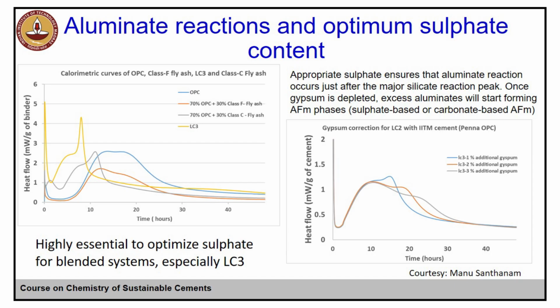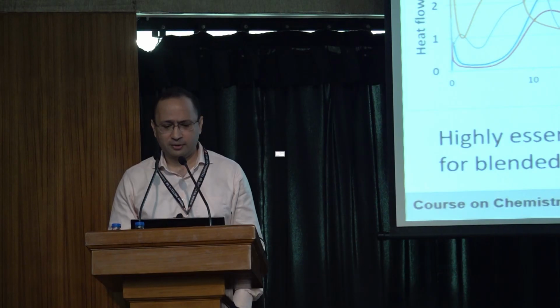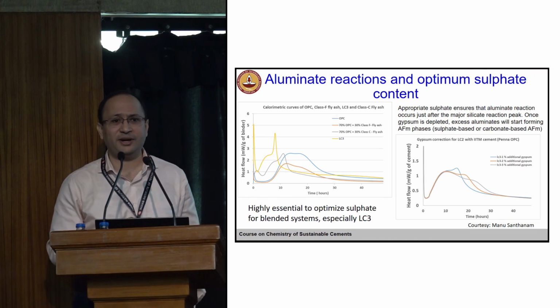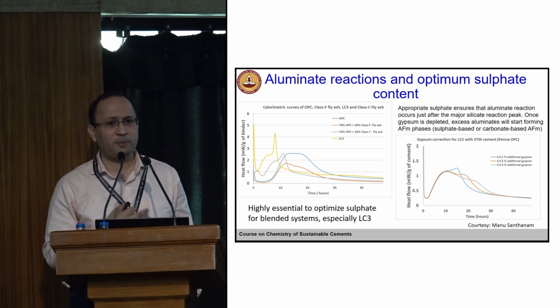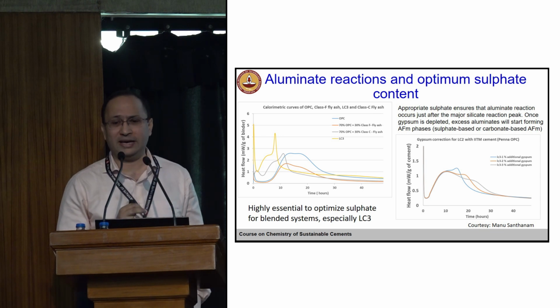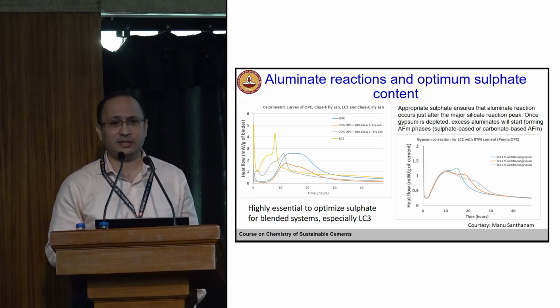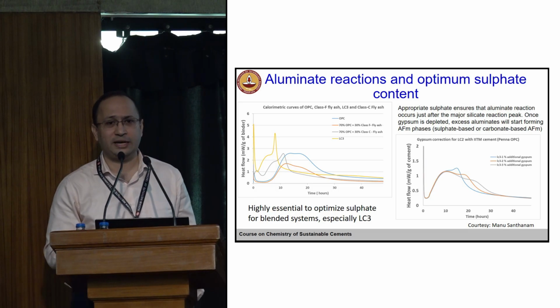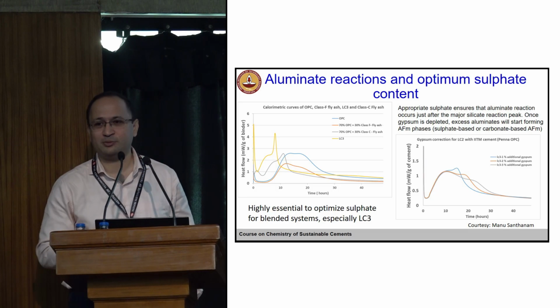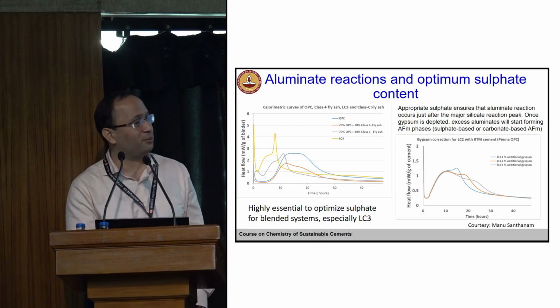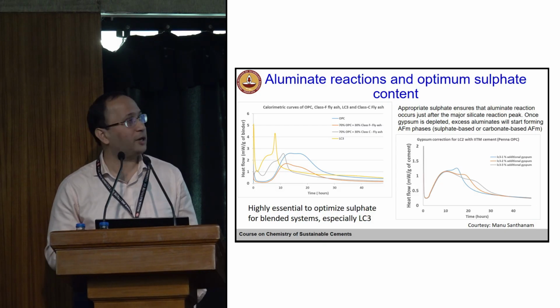Now, there was a discussion about the gypsum. How do you determine how much gypsum to be added, and why is it important? Because it's very, very important to have optimum sulfates, right? Traditionally, people used to optimize the strength. So you add 0.5%, 1%, 1.5% gypsum to your clinker and see which gives you the maximum strength and optimize your strength. But there are more scientifically accurate methods.